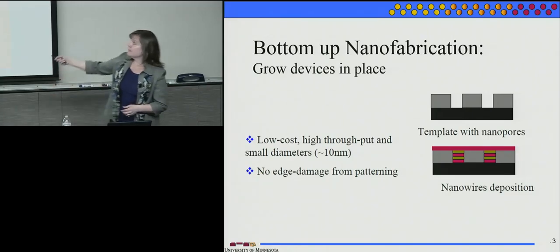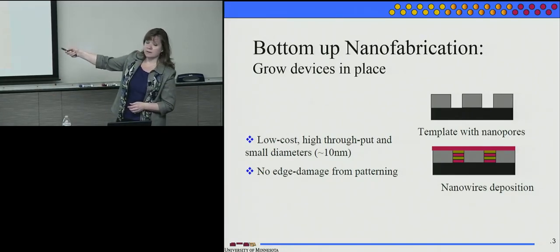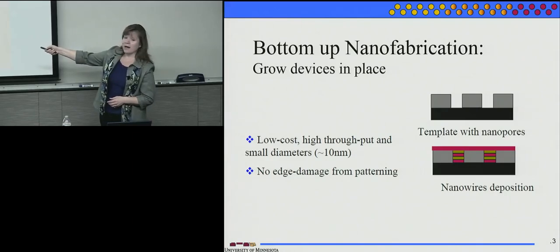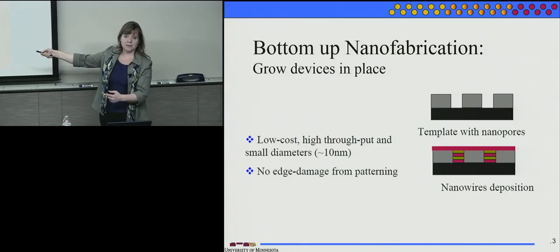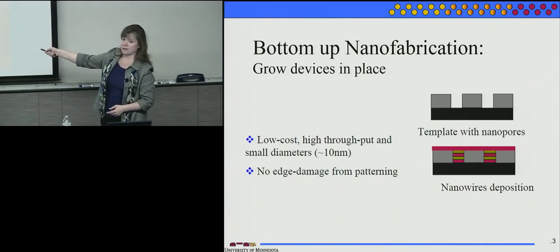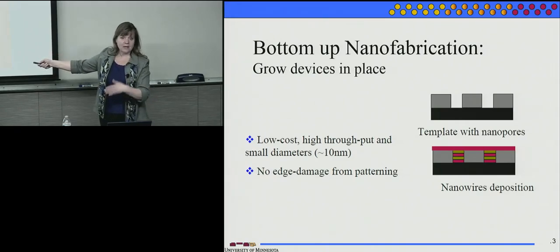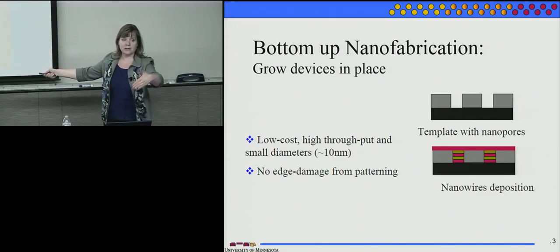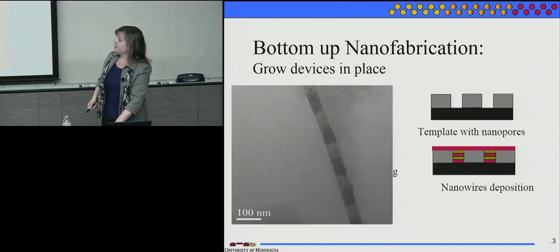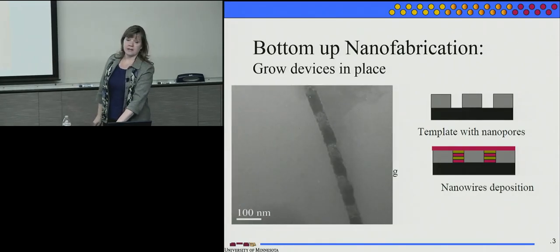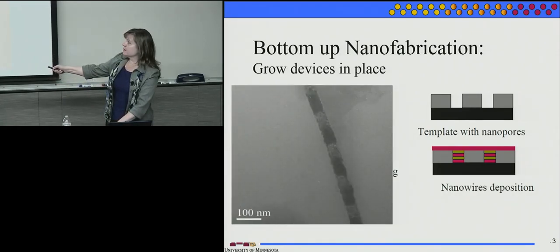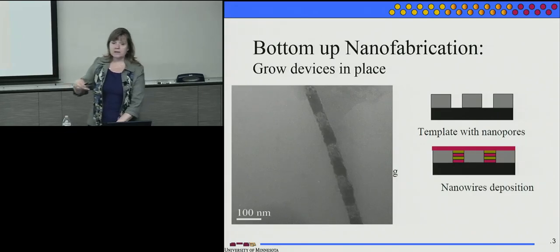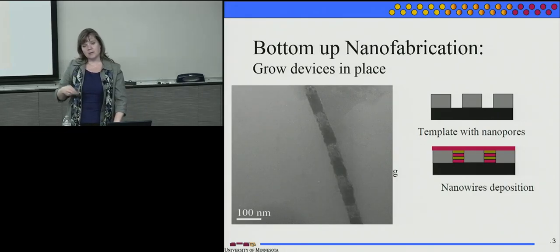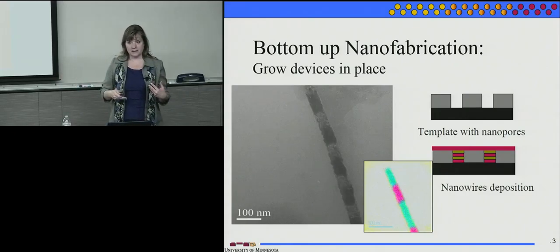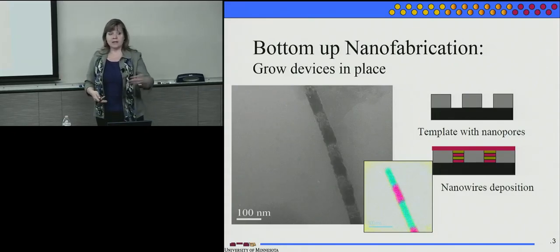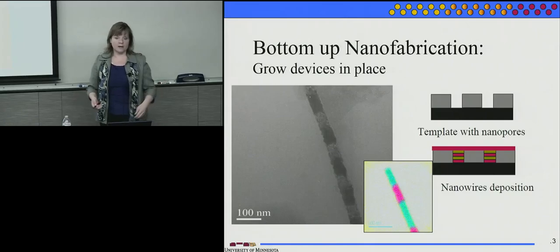All right, so if instead we have a template that has holes in it, and we start at the bottom, instead of having atoms come from the top, we actually charge this and attract ions, now they deposit on the bottom from a solution and build up the pores. And then you can end up getting a nanowire that looks something like this. Now, the interfaces are good, but you can see there's sidewall damage because this had to be removed from the oxide in order to image it. And that removal process is corrosive, so the wire gets corroded.